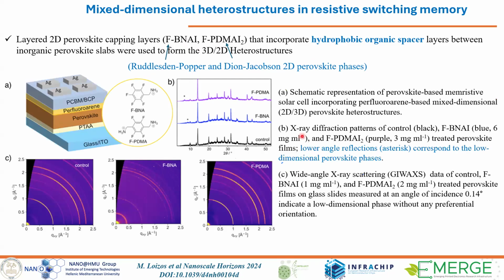Okay, we implemented X-ray and wide-angle X-ray scattering, WAXS, in order to identify what we have deposited on top of our perovskites. So these X-ray curves here indicated that we have a low-dimensional phase that is formed, a quasi-2D, let's say, phase on top of our 3D perovskites. So this is a heterostructure.